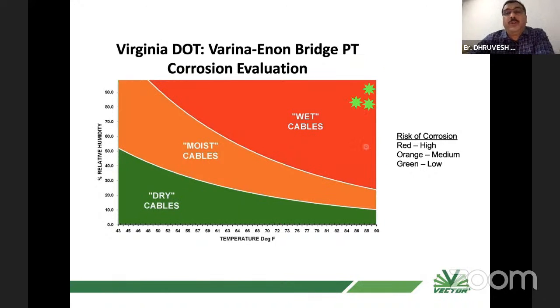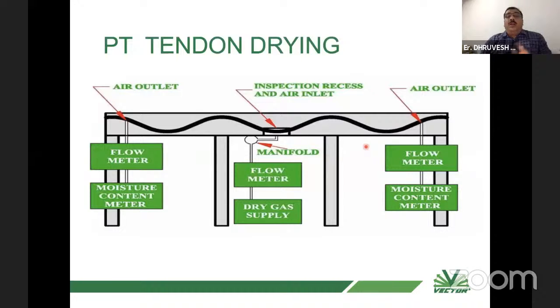So it's directly related to the moisture content in the grout. With high moisture content the corrosion rate will increase, and with low moisture content the corrosion rate will be low. You can do drying. This can be used for unbonded tendons also. In unbonded tendons there is no grout, it's all void. But if there is moisture, it will definitely lead to corrosion. So in the case of grouted tendons or unbonded tendons, you can do drying of the duct.